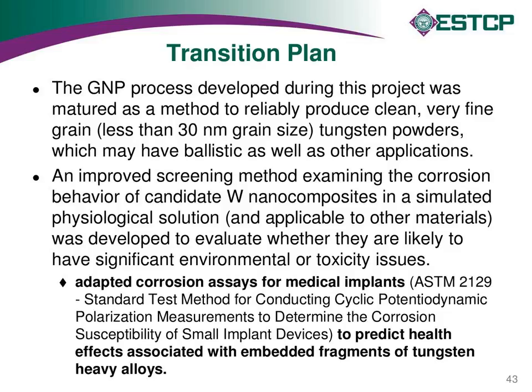The GNP process itself was further improved. Maybe Kirk can talk a little bit more about it, but it's a nice technique for producing very clean, very fine grain-sized powders. Certainly we didn't have that before. In general, ARL has relied on nano powders that we obtained from China. So it was very good to have another source of supply and a process in-house so we could look at some of these materials. And the Chinese stuff was usually very high in oxygen, so that was often a problem.